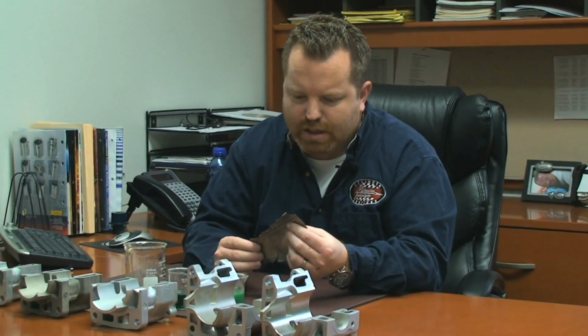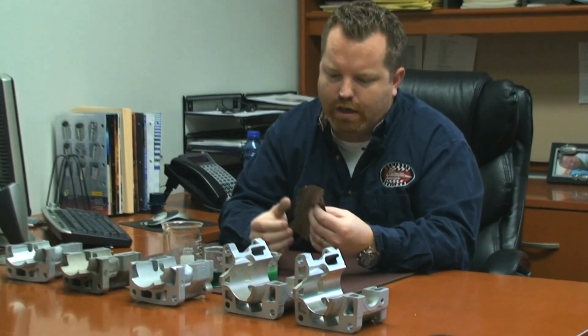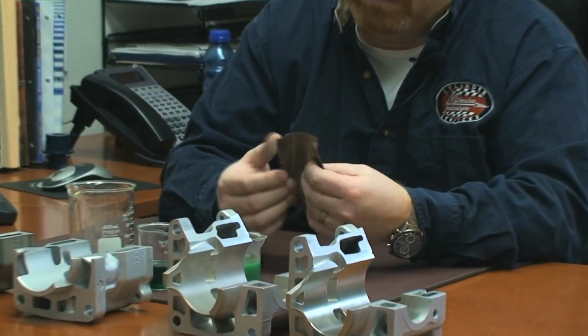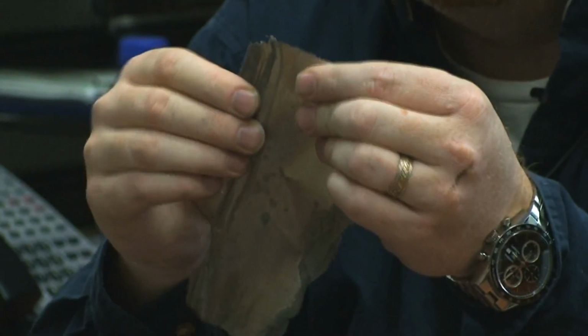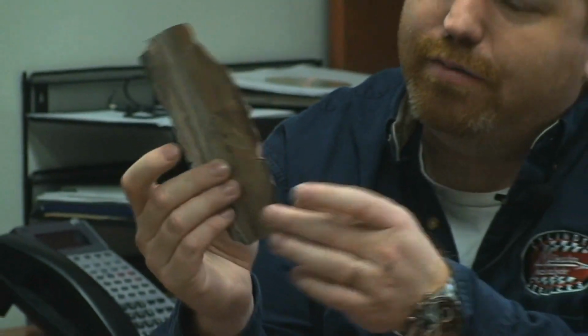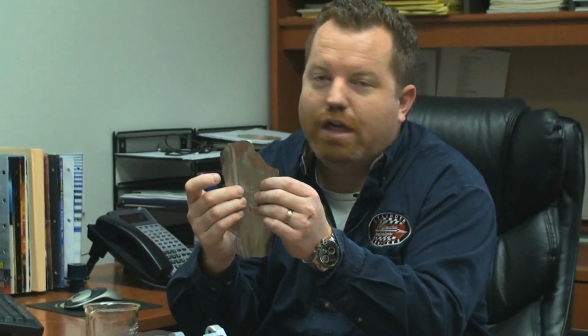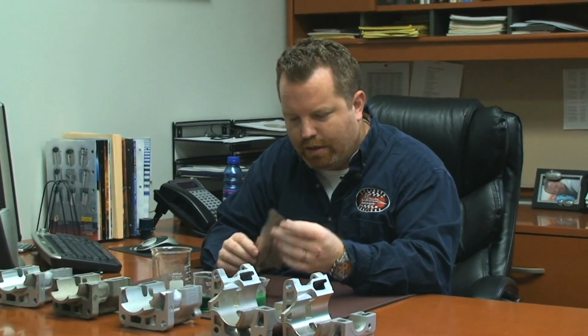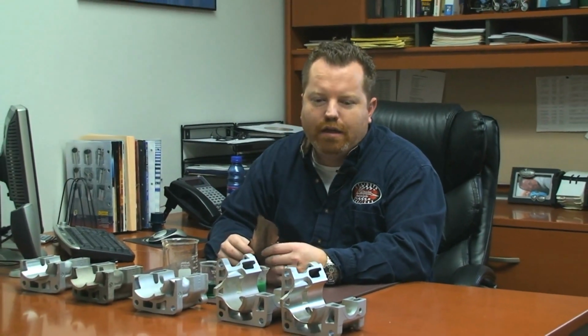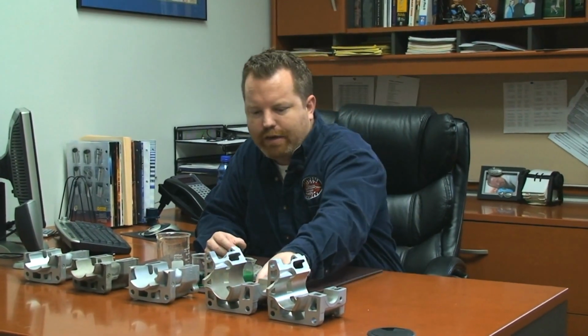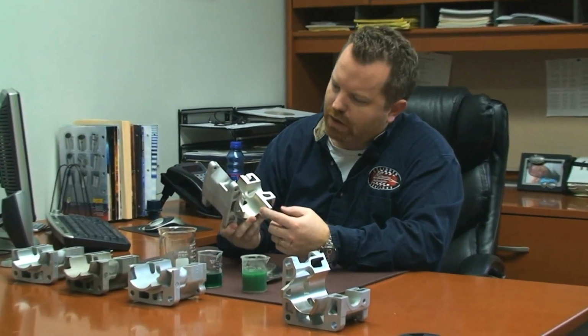The coating, nickel silicon carbide, is very thin. The average thickness that we put on is about 3 thousandths after it's honed. This coating here is about 10 thousandths, but you can see that it's quite flexible, and these are coming off of some of our plates that we use. So you can see what the coating looks like when it's not on a cylinder. Once it's applied, it looks a lot like this. I've got it on a cylinder right here, so you can see what it looks like.